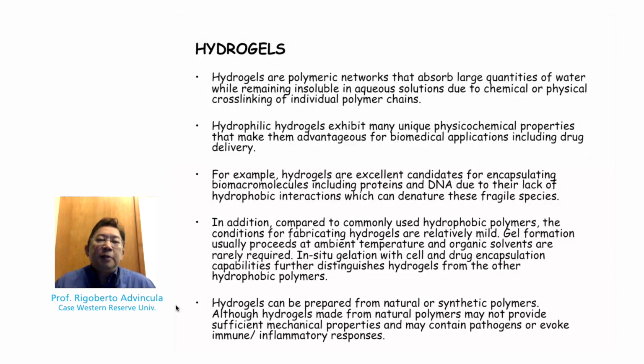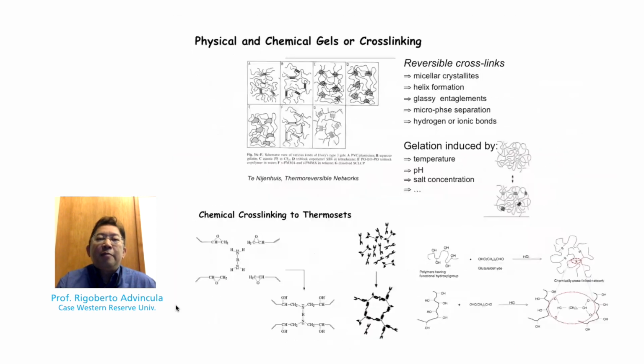So a hydrogel essentially is a combination of either a physical cross-linking or a chemical cross-linking. A physical cross-linking means it's reversible. A chemical cross-linking is an irreversible component, meaning you form or reform a covalent bond. So just to show you what a hydrogel would do, and again, hydrogels here can be used for the polymeric drug excipient, drug delivery, as well as scaffolds for tissue engineering.